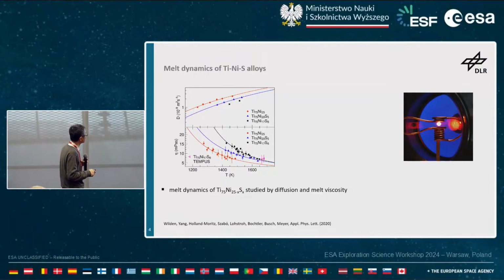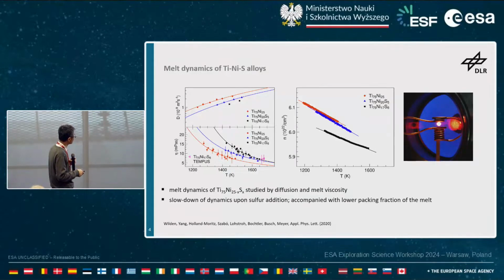And similarly, if you look at the transport coefficient, they show similar trends. So basically, the melt dynamics slowed down with sulfur addition. What is interesting is that usually you would imagine that if a metallic liquid gets more viscous or the dynamics gets slower, they are more densely packed. But this is not the case in these sulfur-containing alloys.